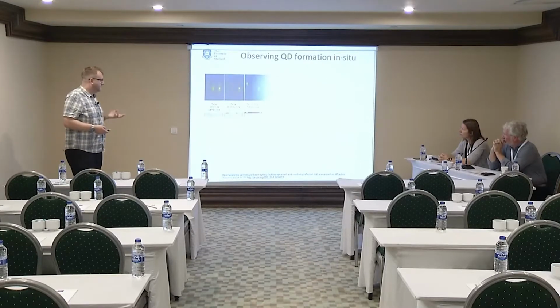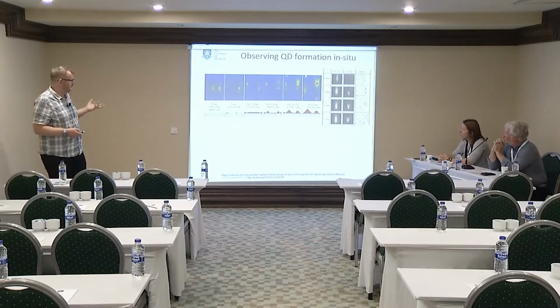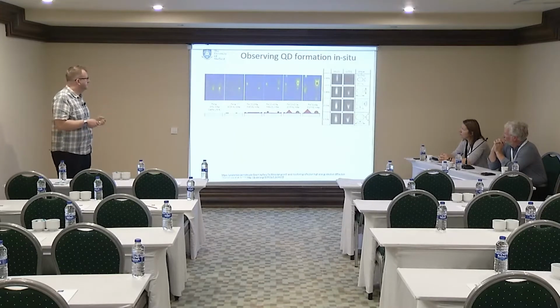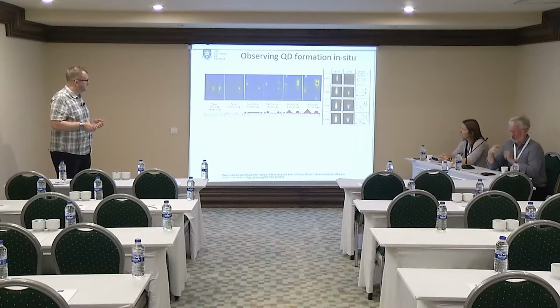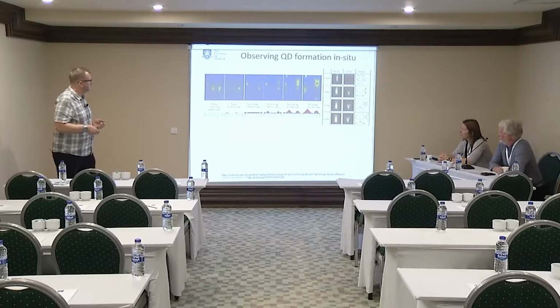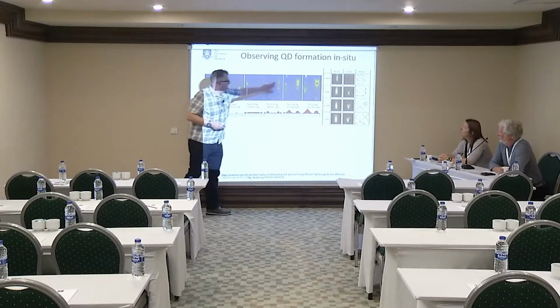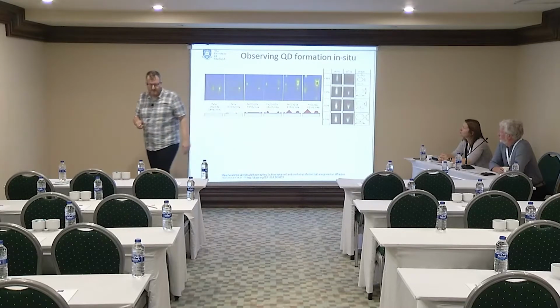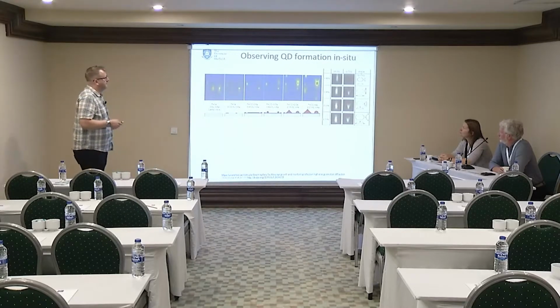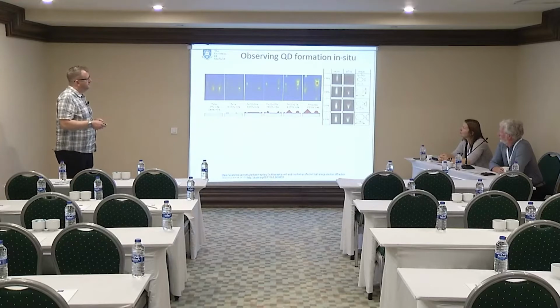We can watch the quantum dots forming in situ. This is the one advantage, if you like, of MBE over other techniques. We can look at electron diffraction on the surface, starting off from a streaky pattern, and as we progress, we start off growing this initial layer, and then eventually when the island formation happens, you start to see an increase in the intensity at this point. We can follow that through, and we end up with chevrons, which are showing effectively the shape of the quantum dot. And if we look in the two crystal directions, we can infer that the dots elongate.